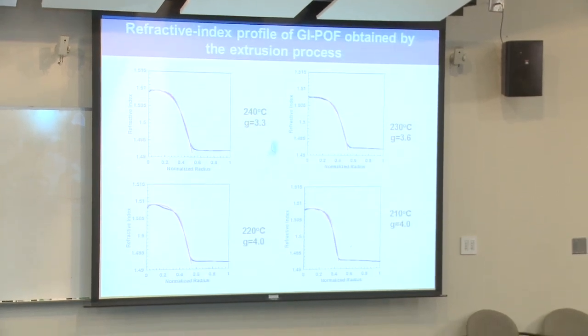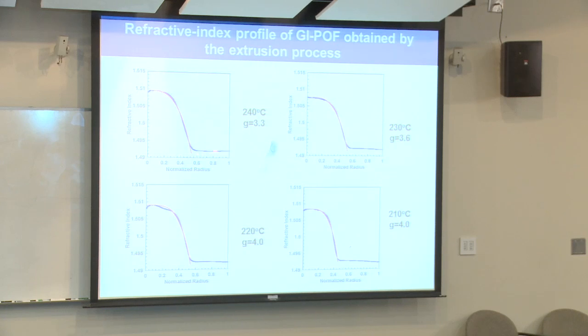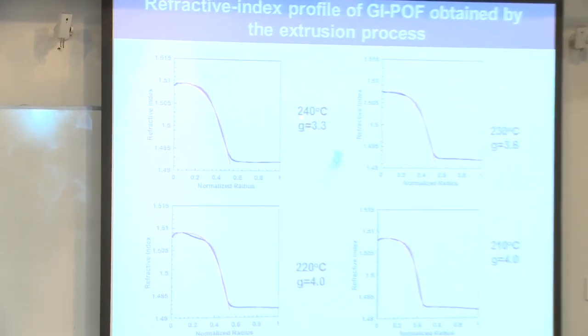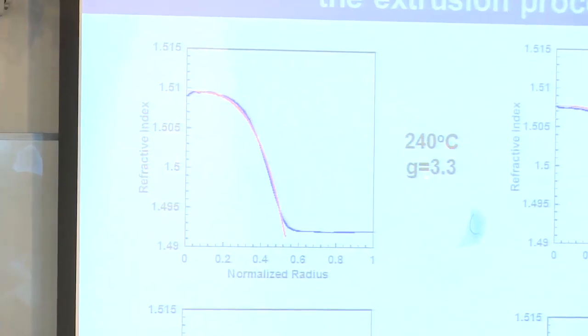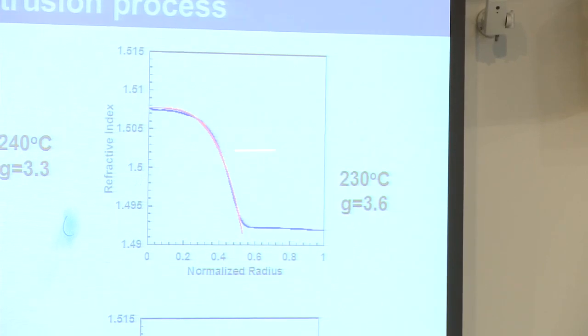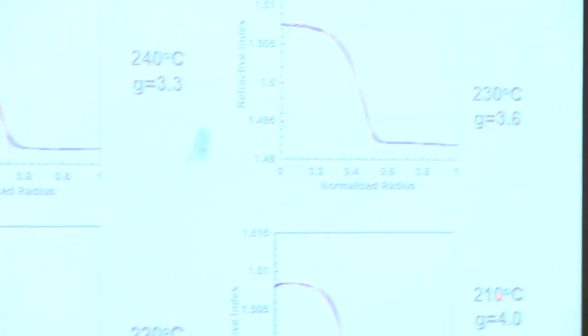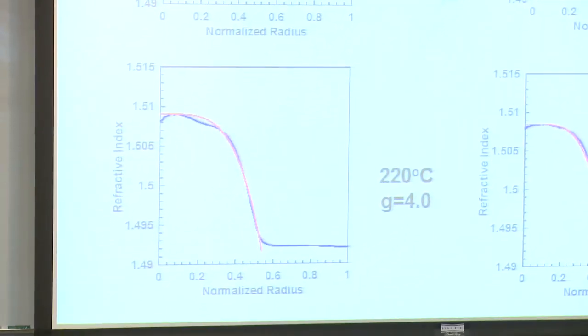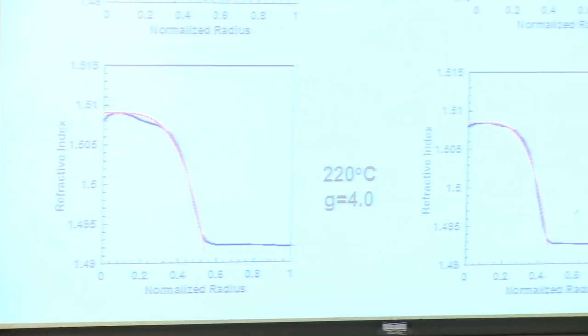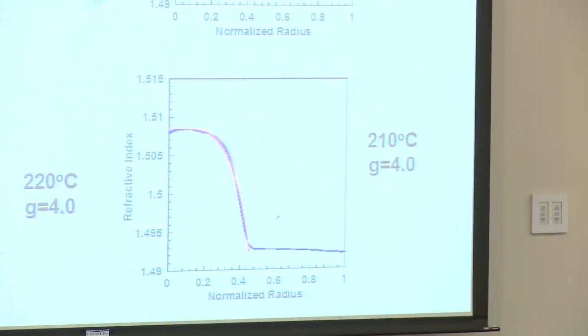Now this is the experimental result of the refractive index profile of the resulting fiber. When the temperature is 240 degrees centigrade, the index exponent of the index profile is 3.3. By changing the temperature of the diffusion zone, we can control the index profile very precisely.